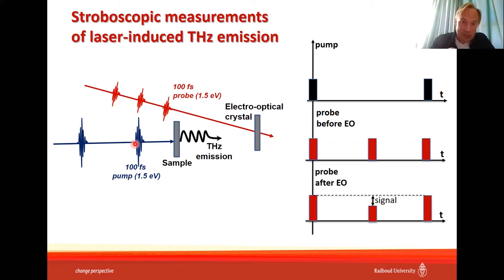Very important, in order to gain a reasonable signal-to-noise ratio, you have to repeat this experiment many times. So that's why the pulses fly with a repetition rate of 500 hertz in the case of pump and 1 kilohertz in the case of probe. So basically every 2 milliseconds we repeat this experiment, accumulate the data during several seconds, and in this way we can get a decent signal-to-noise ratio. But the price we have to pay for this is that we can study this process only if we make sure that after each pump pulse the sample arrives to the very same state. So basically, we repeat the very same situation many times, relying on the knowledge that after the pump we bring the sample to the very same state, so that we can excite it from the very same state again. Only in this case can you trust stroboscopic measurements.